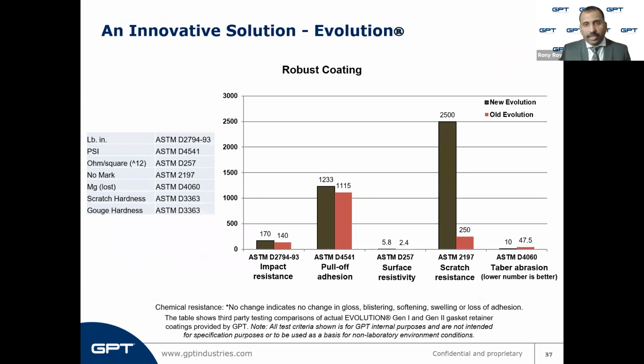Another important thing to talk about is the coating, since people will be unfamiliar with the coated isolation gasket. When we started evaluating coatings for potential use on this isolating gasket, we looked at several tough coatings available in the industry, like the 3M coatings, the PTFE coatings. So many coatings are available out there. The 3M coatings proved to be one of the toughest in the industry. And as you can see in this graph, the ASTM 2197 scratch resistance test was one of the tests that all the coatings that we had evaluated were subjected to.